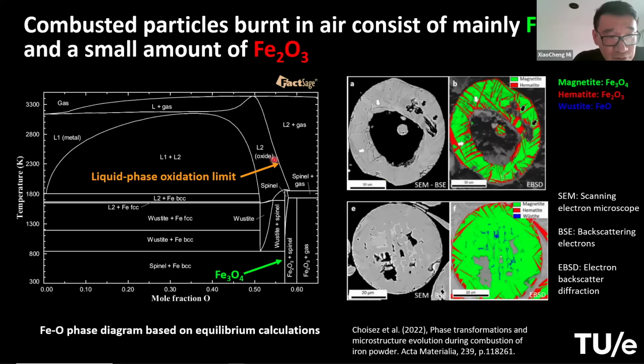And you can see this boundary actually also goes a little bit beyond Fe3O4, which means once it cools down, it actually contains more oxygen than the solid phase can hold. And this is why we see these kinds of cavities formed, because the oxygen needs to be repelled out of it. And only in solid phase, if you keep it warm enough and supply oxygen, can it further oxidize to hematite, the highest oxide product.